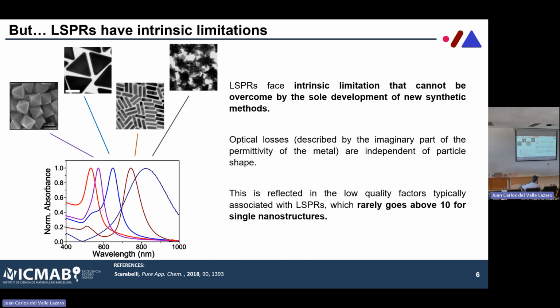In the sense that, of course, everything comes with some drawbacks. And in the case of localized surface plasmon resonance, the problem is that these resonances are associated with a lot of optical losses, which basically means that these plasmons are very short-lived. They live for a very, very short amount of time. And this basically translates at the end of the day in low quality factor.